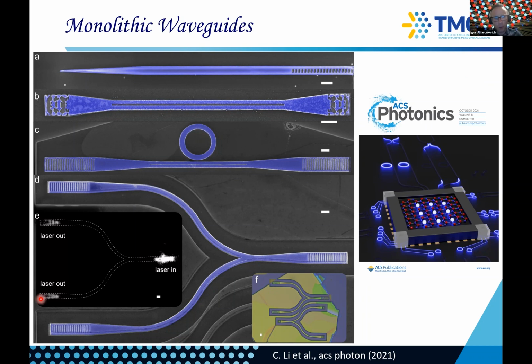In terms of fabrication protocol, we use mostly, as you probably can guess, reactive ion etching and e-beam lithography. The interesting bit here is the choice of mask. We're still playing around. Sometimes we use metallic masks that are a bit easier. Sometimes we just use the normal resist and liftoff. But we tried a few times directly putting a metal mask and etching through, which works quite well.